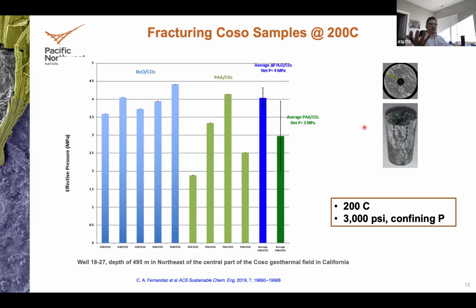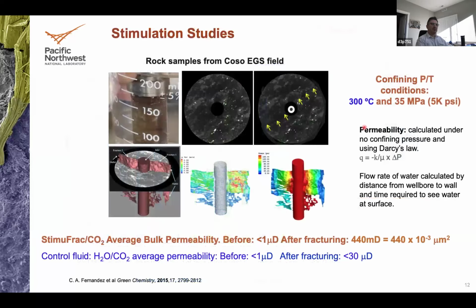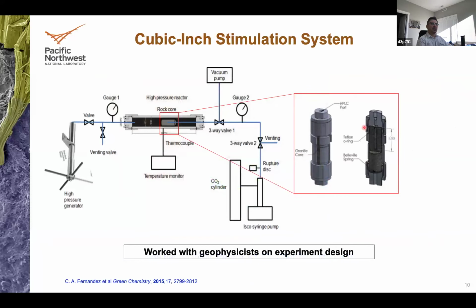So we ask, is the volume expansion actually creating some local stress, so that when we measure the pressure at the pump right here, we see a lower pressure when we fracture with polymer solution CO2 than with all the other fluids, including water CO2? Is it a localized pressure that doesn't communicate to the pump? We should fracture the rock at the same pressure independently of the fluid, but it doesn't seem to be the case. So what could that be?